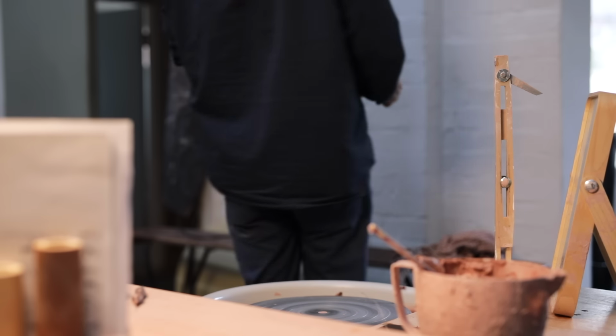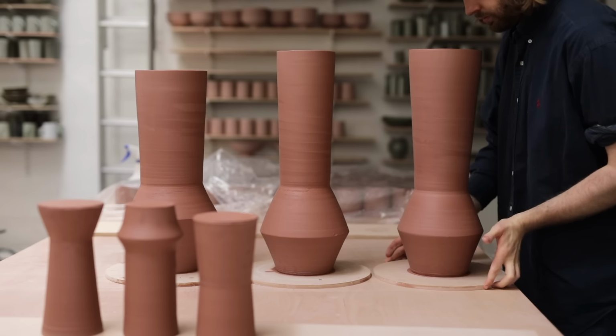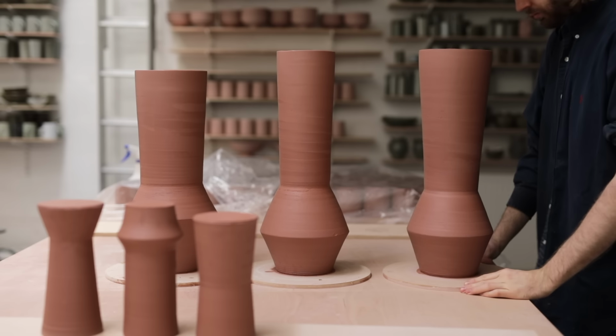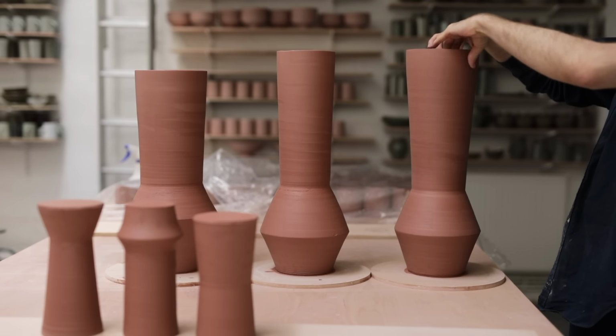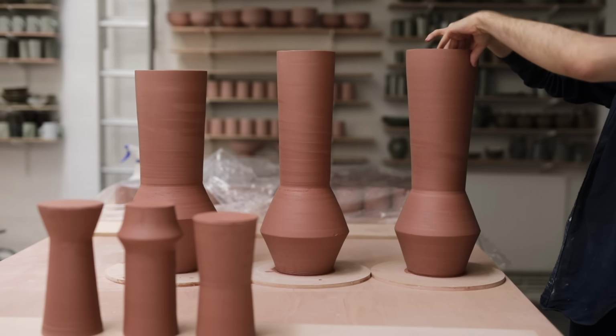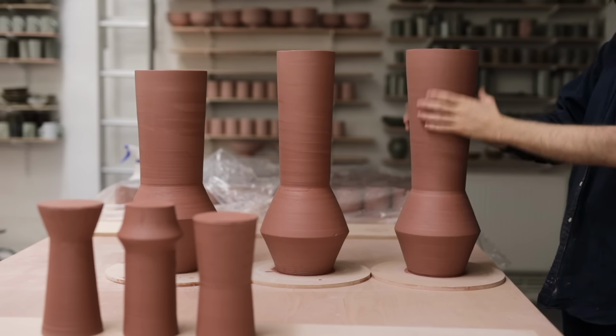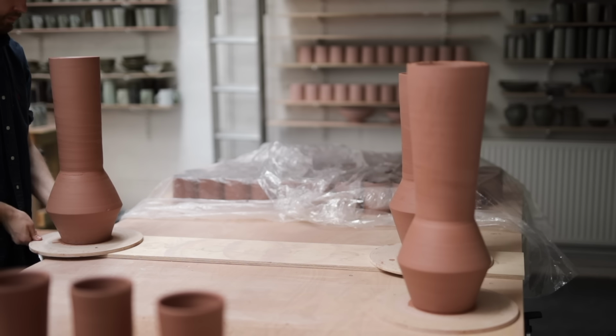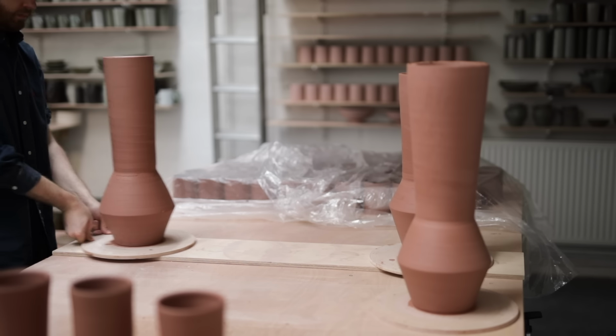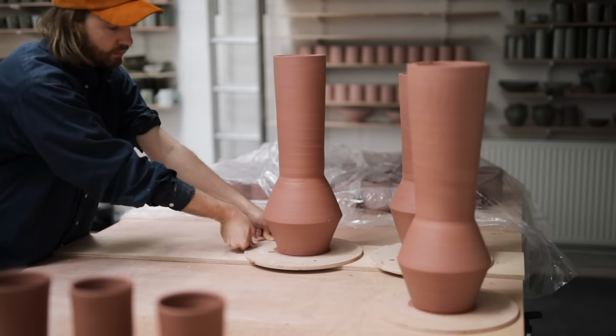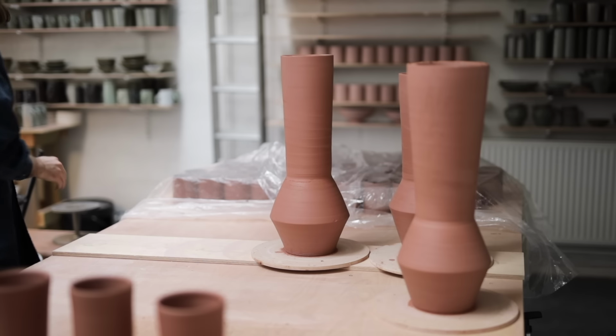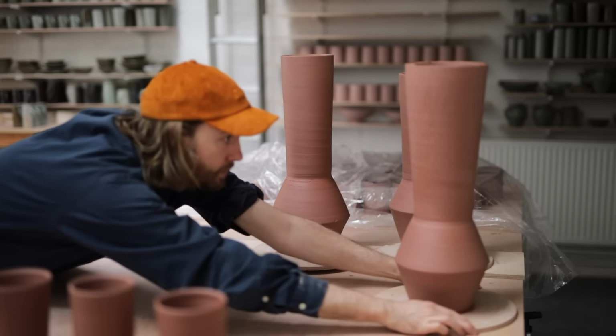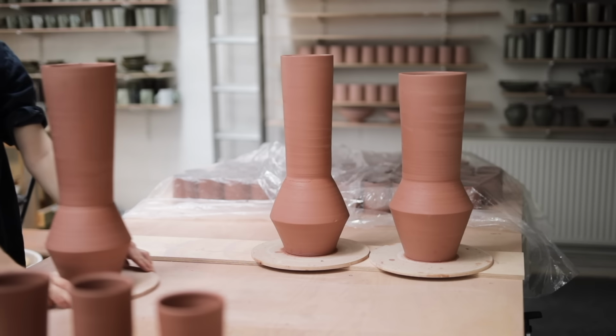And as these were quite thickly potted, they took some time to dry out to the point where I was happy to trim them, and for one night I wrapped the lower section in plastic so that the upper walls could hopefully dry out and match the base below. And this was a really bad idea, as my studio is quite drafty, and when I came in the following morning, a few of these were just ever so slightly leaning to one side. I can sometimes get away with leaving my mugs out overnight, but with larger pots like these I should have really been more careful.